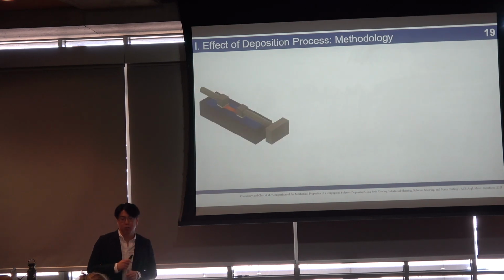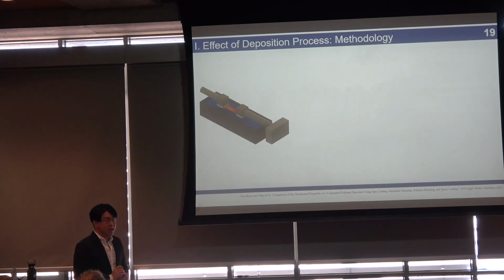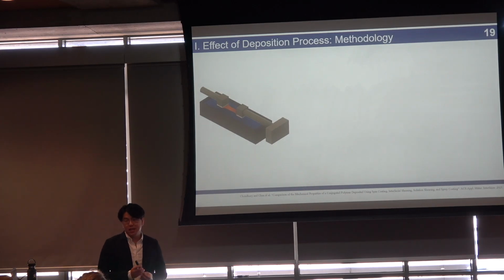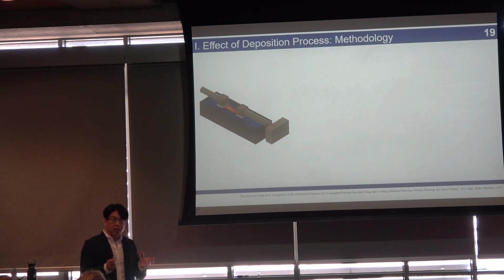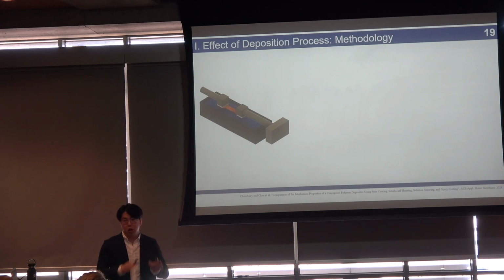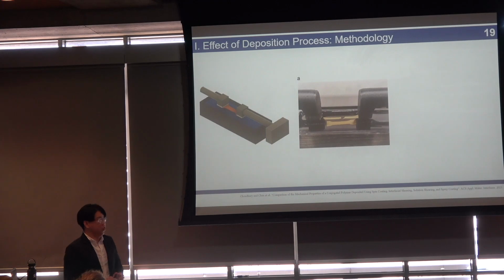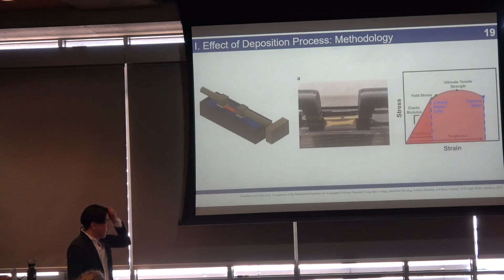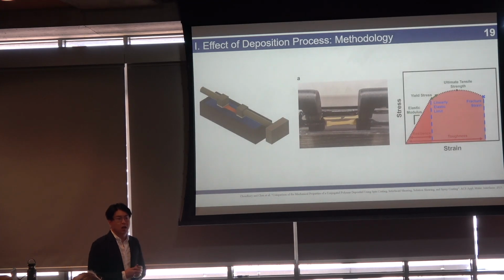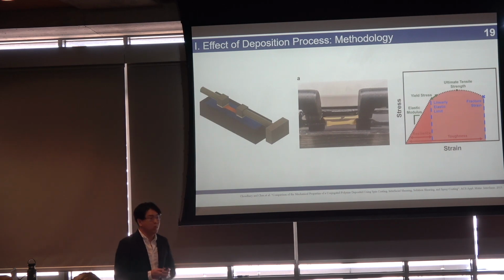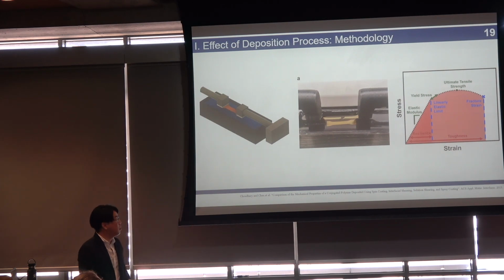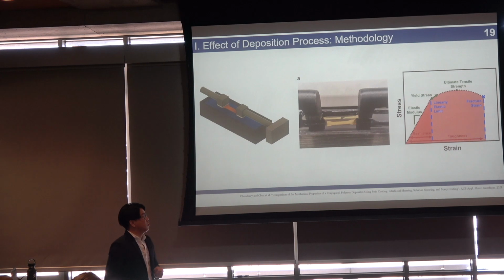So to measure the mechanical properties, we use a technique called film on water. So in this technique, because your conjugated polymer is not soluble in water, we can spin a water-soluble layer below it and dissolve that layer so that this polymer floats on top of the surface of water, and we can stretch it. So it will look like this. And from here, we can use the geometry of our dog bone, and we can use the measured load and travel to get a stress-strain curve.